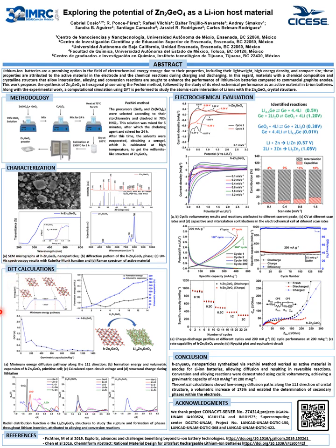The first image illustrates the minimum energy diffusion pathway for the first lithium ion, Li. It shows a minimal energy barrier of 1.42 electron volts along the 111 direction, where a tunnel in the structure allows the ion to be surrounded by oxygen atoms, facilitating easy diffusion without altering the structure. After identifying the pathway and minimum energy positions, lithium ions were inserted into the material. For this material, it was calculated that up to 14 ions can be stored per molecular unit, providing a theoretical capacity of 1,400 mAh per gram.